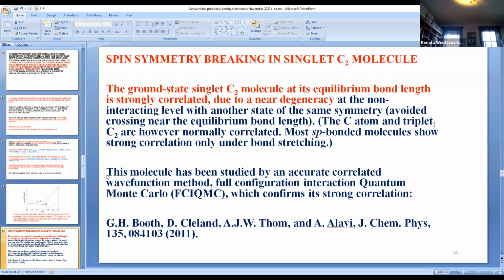It's strongly correlated because there's a near degeneracy at the non-interacting level between two states with the same symmetry, causing an avoided crossing near the equilibrium bond length. It's not unusual for this to happen in sp-bonded molecules when you stretch the bond very far, but here it happens at the equilibrium bond length. Singlet C2 has very strong correlation compared to other similar molecules. The carbon atom, on the other hand, and the triplet C2—the spin-one excited state—are normally correlated.